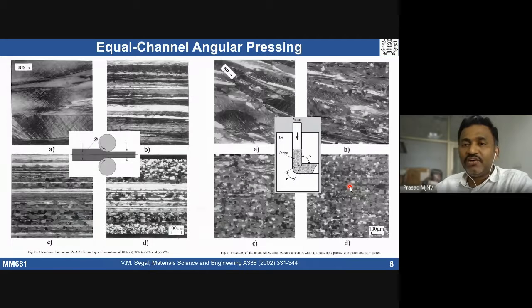Any doubts here? When you rotate it, you can develop an equiaxed microstructure much earlier because we are creating so much vortex. The metal flow undergoes a vortex every time you change the direction, so that can lead to a much finer grain size. If you take route BC or route BA, those two routes can give you a much finer grain size even for the same number of passes.